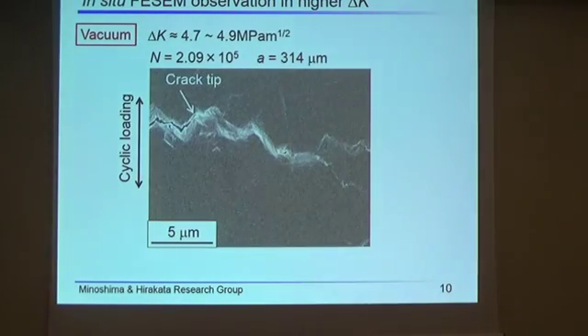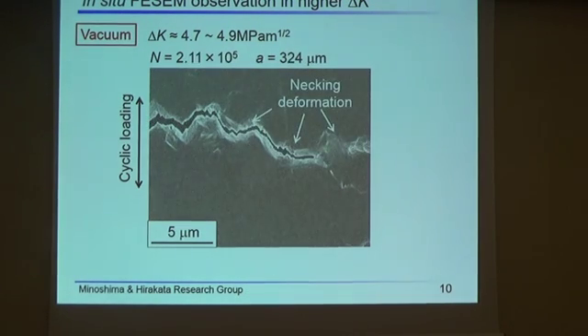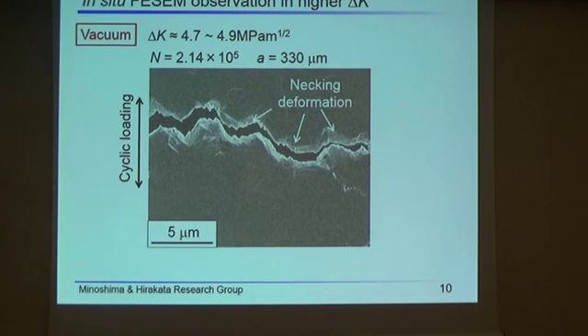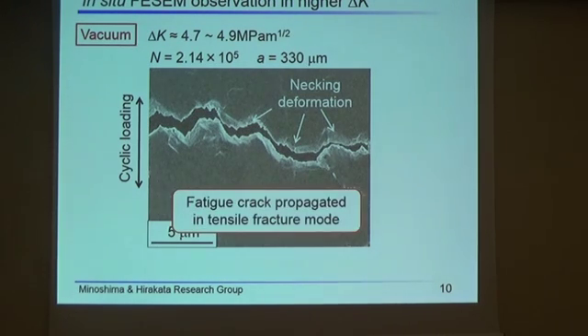Next, this slide shows fatigue crack propagation in higher delta K. This is a crack tip, and strip lines were widely observed ahead of the crack tip. By applying cyclic load, the fatigue crack propagated through these strip lines, and necking deformation was observed along the crack path. This result indicates that the fatigue crack propagated in tensile fracture mode.